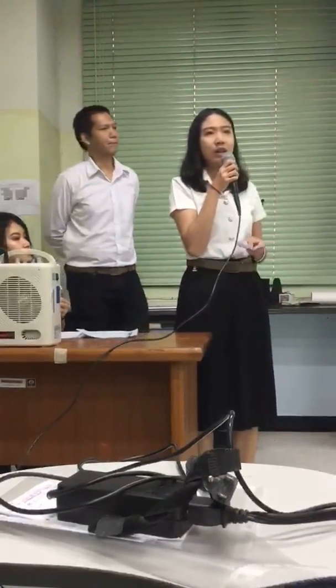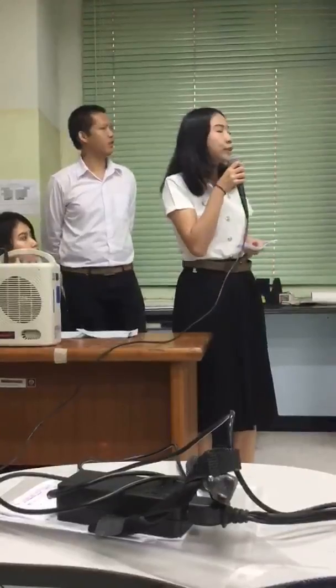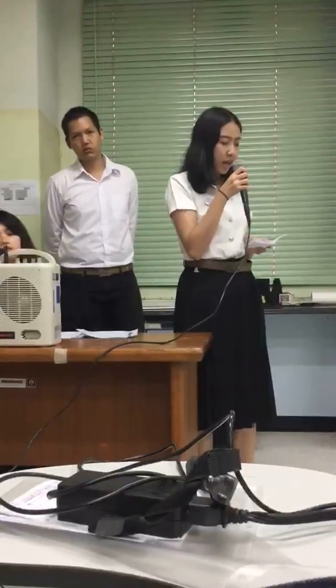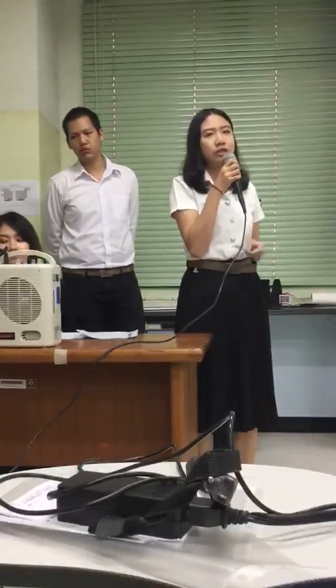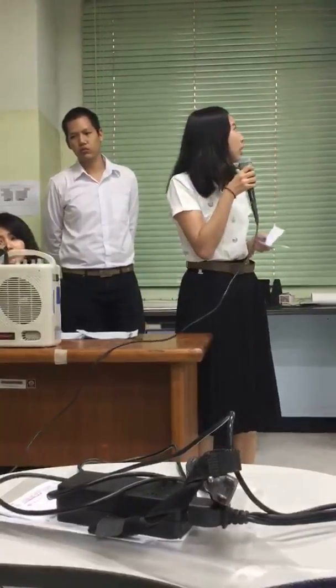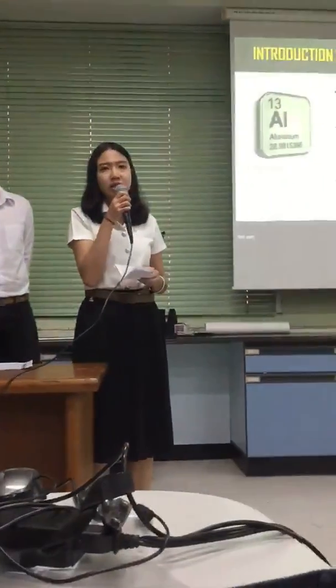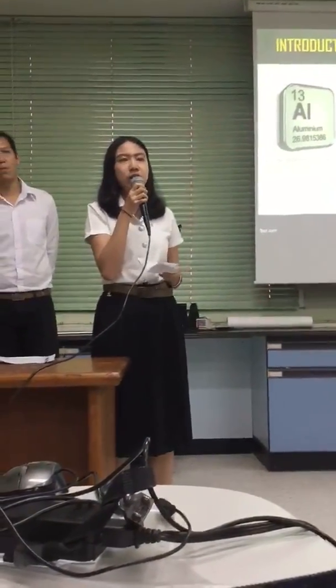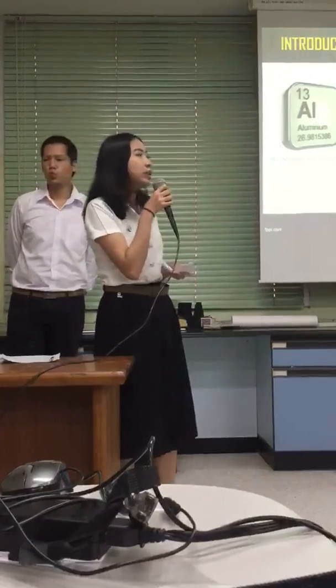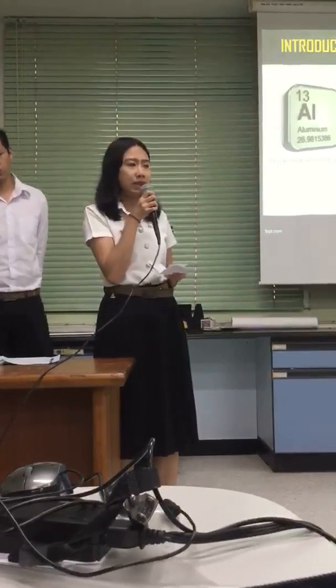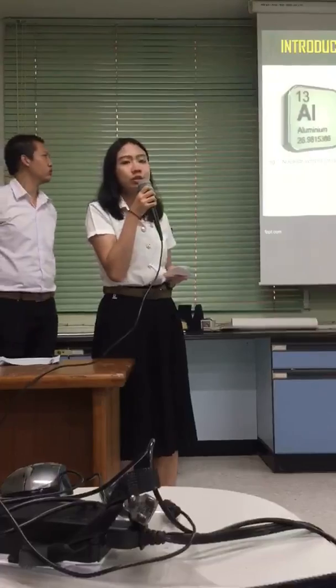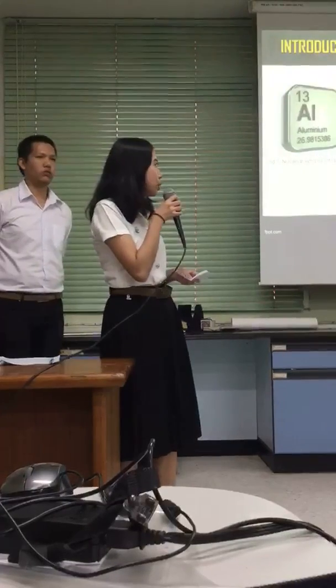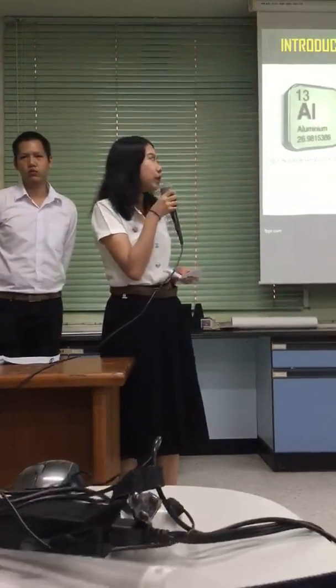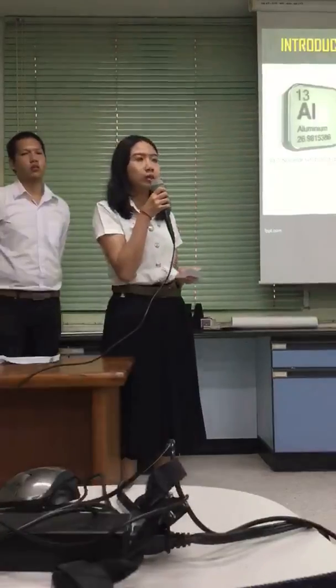When zinc oxide is compared with indium tin oxide or ITO, it is found to have high transmittance, high chemical stability, non-toxic, and low cost. This research studies aluminum doped in zinc oxide structure with various concentrations. The concentration of aluminum is suitable at 1 atomic percent. When zinc oxide is compared with AZO and ATZO, it is found that ATZO has lower resistivity.